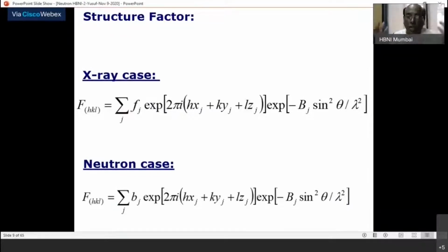Okay. Now you may say, in an unknown case, we don't know what is magnetic. You give some moment and see whether you are able to explain your observed pattern. That is the way to go. So-called magnetic atoms also sometimes may not be ordered. Then that information comes; you give it and see. Your analysis will tell you that this one, though supposed to be magnetic, has no observable moment. So that is the message. But in simpler language, when you talk about the magnetic structure, you count only the magnetic atoms or ions. Okay. So this is called your structure factor.